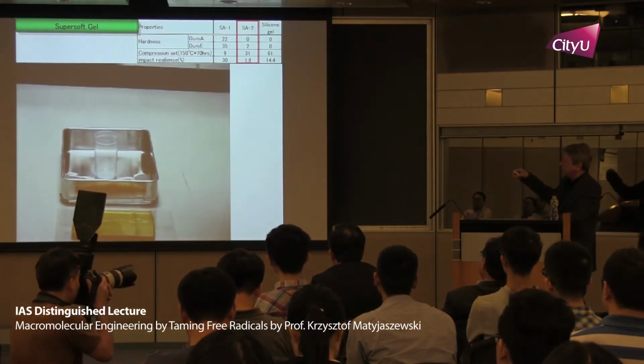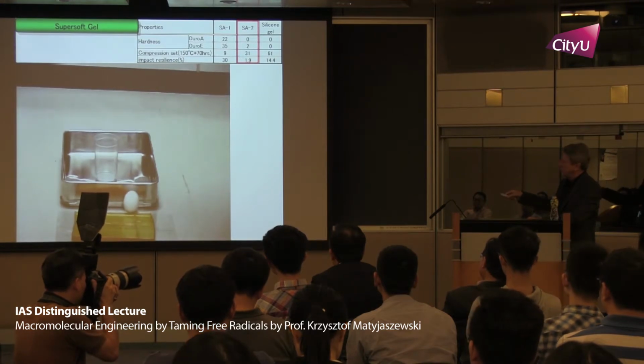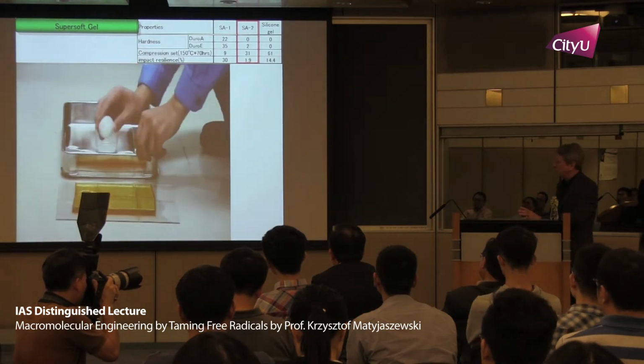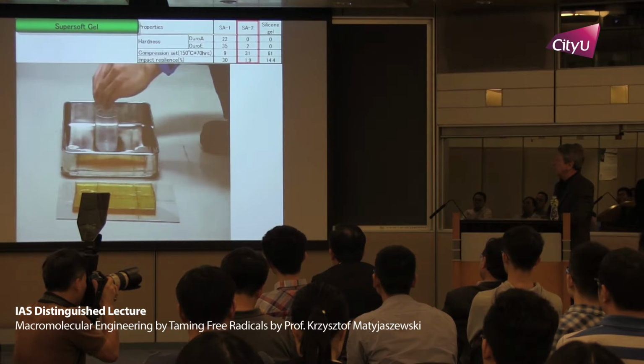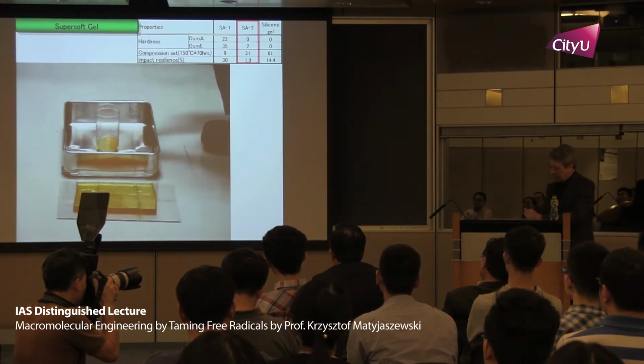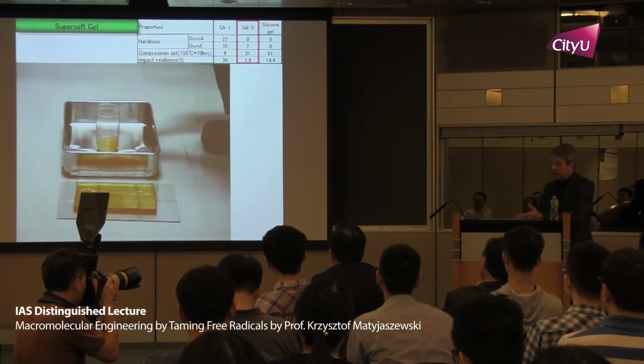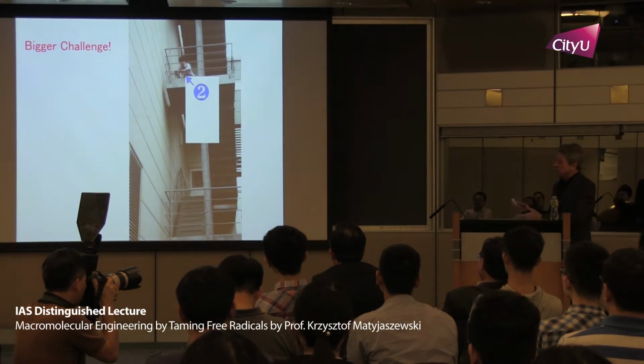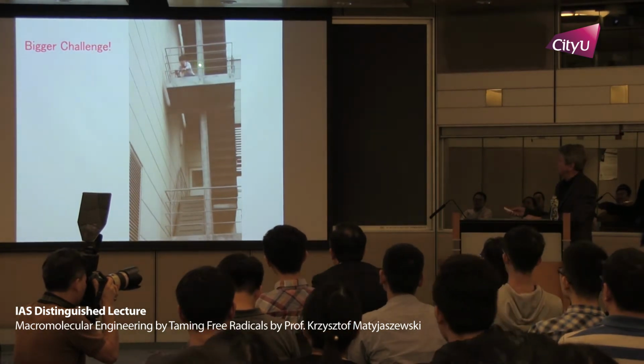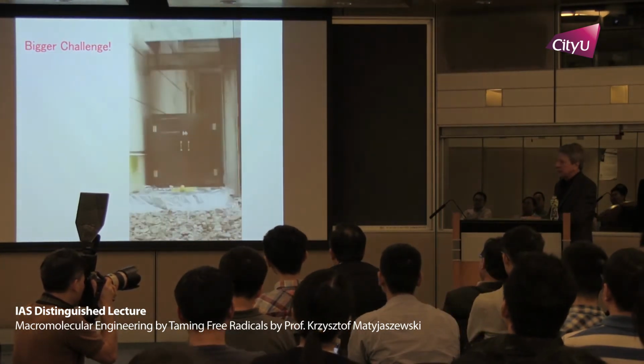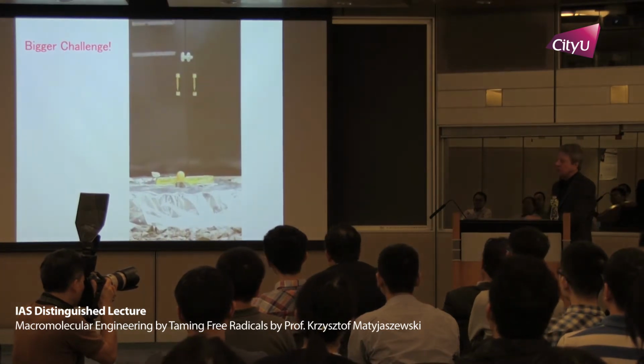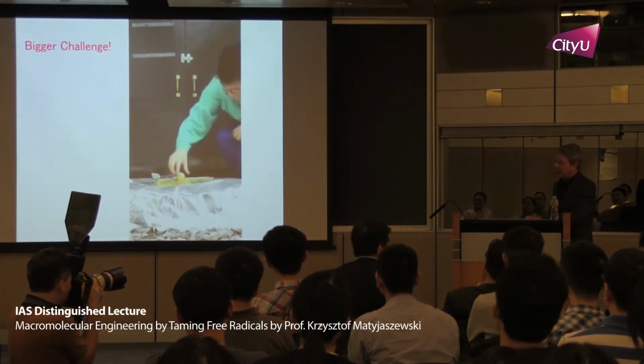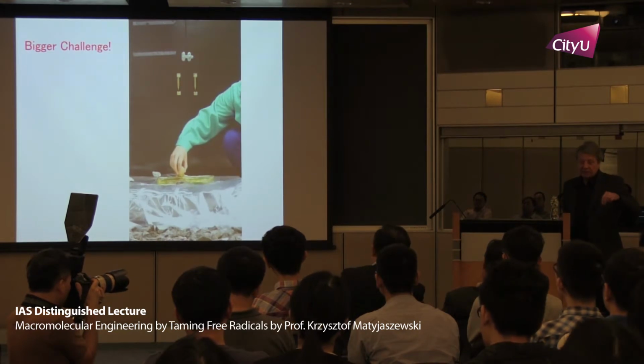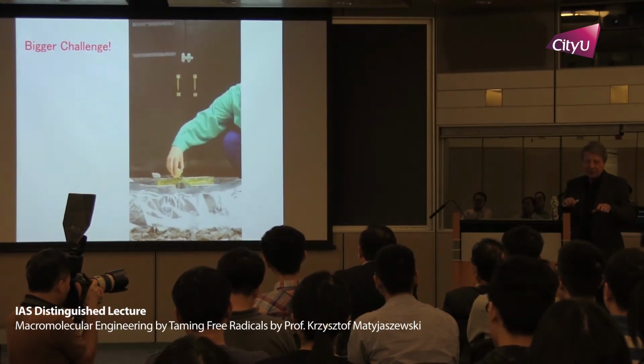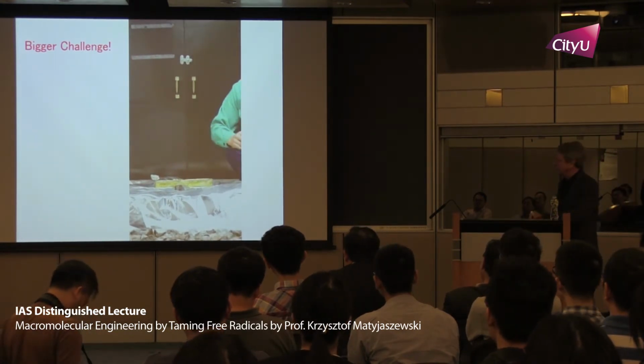So here's an example with a Japanese egg. It is dropped from a height of maybe 1 meter, and this is a raw Japanese egg, as you see, and it survived. And if you are a little bit more ambitious, you can make a bigger challenge. You go on a third floor, drop this egg, and it survived more or less to the same degree. In fact, the biggest challenge is how you can center it, so that it would not land on the top, because otherwise it would obviously fail.